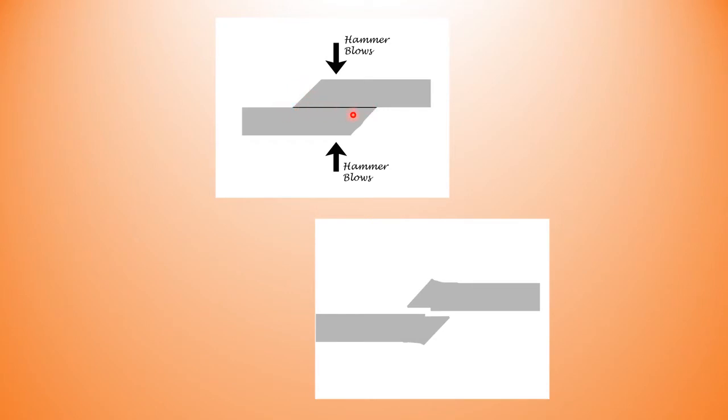A long overlap can only serve to give you more space to entrap some debris that will cause your weld to fail or make it more difficult to get a nice even same color on your two pieces. Keep this step shallow so you don't create a shear plane in the middle of your piece.